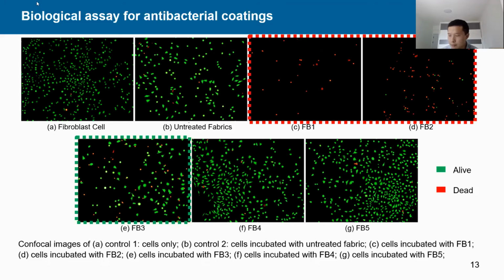Figure B shows that the PET fabric itself does not influence the viability of cells. And FB1, FB2 show high toxicity, killing all cells. Sample FB3 shows lower toxicity with still a lot of alive cells, indicating a potential of biocompatible coatings for medical applications. The results of FB4 and FB5 indicate no cytotoxicity of coatings made from HMDSO precursor and a mixture of water aerosols.